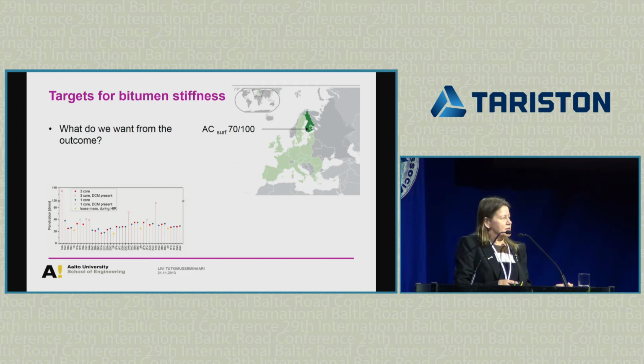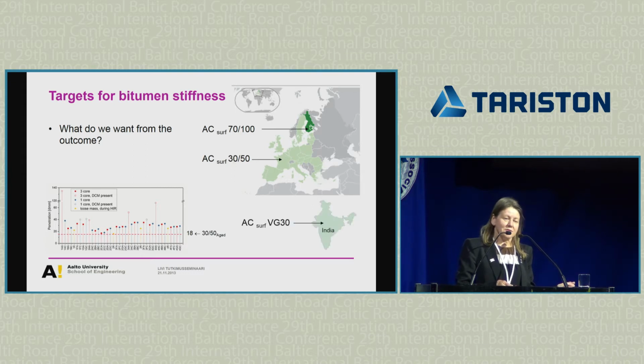So there you see data from an actual road, 26 kilometers. You can see, for the research project that we were doing, how the penetration is changing. But as an average, it seems to be somewhere around 30, maybe 35, something like that. Well, if you are in France, you actually start from somewhere around 30, 35. And then when this kind of mix ages, it gets to somewhere around penetration 18. In India, you start somewhere fairly similar.